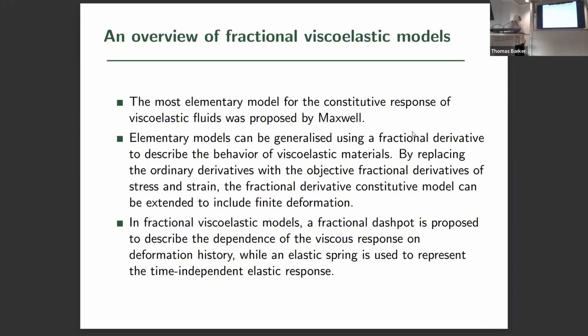The fractional derivative constitutive model can be extended to include finite deformation. In fractional viscoelastic models, a fractional dashpot is proposed to describe the dependence of the viscous response on deformation history, while an elastic spring is used to represent a time-independent elastic response.